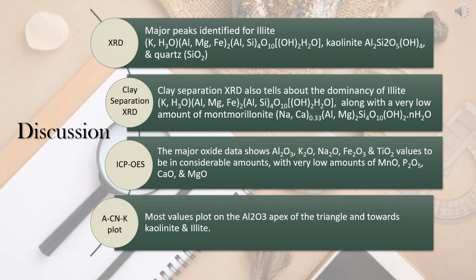ICP-OES data on calculations shows aluminum oxide, potassium oxide, sodium oxide, ferric oxide, and titanium oxide values to be in considerable amounts, with very low amounts of manganese oxide, phosphorus pentoxide, calcium oxide and magnesium oxide, indicating more aluminum present in the samples as compared to iron. This again aligns with the fact that illite is the dominant clay mineral observed in the sample. Also, less iron predicts no clue for specific iron oxide minerals, which is characteristic of carbonaceous shales.